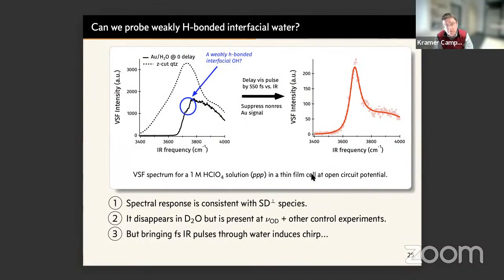Okay, so I told you that to do this experiment, one spatially and temporally overlaps the output of a pulsed non-resonant laser at 800 nanometers and one in the mid-infrared. And if you do that, what you find is the black line. So this is for a polycrystalline gold electrode in 1 molar perchloric acid. And this immediately is somewhat disheartening, right? But if you start to think a little bit about what's going on, it becomes clear.